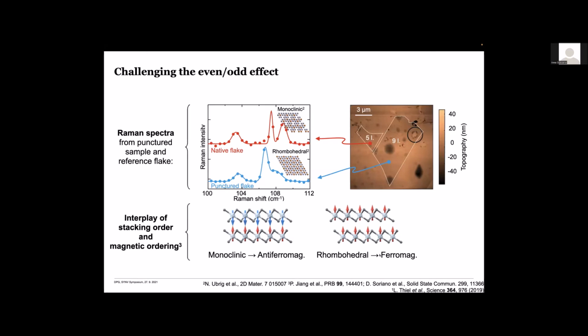So what we believe is happening is that by encapsulating these samples, and I should have stressed that these samples all need to be encapsulated so that they remain air stable, one essentially exerts pressure onto these samples and prevents the stacking order from assuming its natural order, so to say. So we know from bulk that bulk chromium triiodide has this rhombohedral stacking. This does not seem to be the case for exfoliated encapsulated samples, and this is why we get this antiferromagnetic interlayer coupling. And puncturing the flake the way we did appears to have released this pressure and therefore allowed the system to relax or return to its native state.